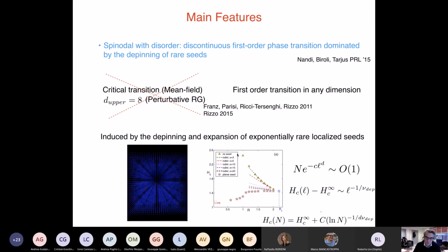We also had analytical arguments, but we tested this idea using the following trick. The idea is that the spinodal in presence of disorder is driven by rare effects. And when you have rare effects, it's super hard to find them doing a numerical simulation. But if you know what these rare effects are, then you can put them in by hand, and you can see that they have a drastic effect on the phase transition. This will validate the fact that they are important for the phase transition.